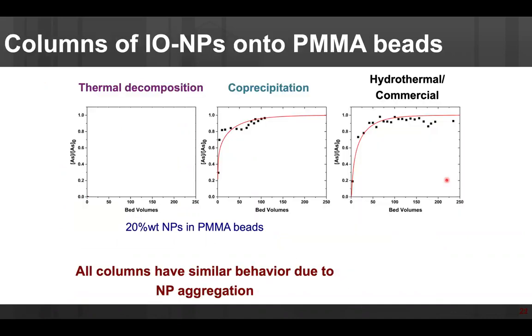When I try to do columns in here, as you can see, the co-precipitation and hydrothermal column experiments look horrible. The arsenic comes very fast. But when I do the thermal decomposition, I cannot even flow water. Why? Because the thermal decomposition of the nanoparticles leaves a surface coating that is organic. So I created a very hydrophobic material.